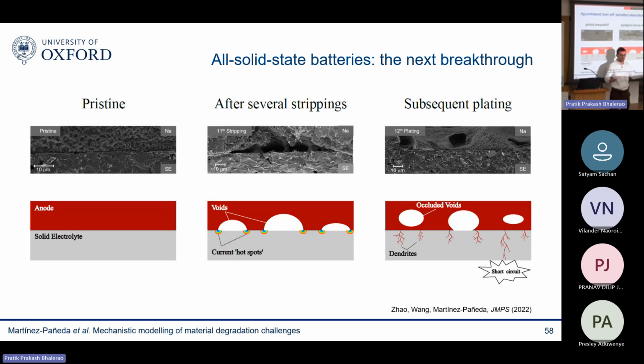How are those dendrites formed in the first place? You see it here. These are images from Peter's group at Oxford. So initially you have an interface that is quite smooth. It's not perfect. Nothing is perfect in life. But you have your sodium or lithium metal, and this is the electrolyte. Every time you discharge your battery, you do stripping. So you take away your lithium ions, and then you generate voids. It's kind of corrosion. You're removing material. And ideally, you want to remove it uniformly, but because your interface is non-uniform, you are generating those voids. And then when you charge your battery, you have plating.